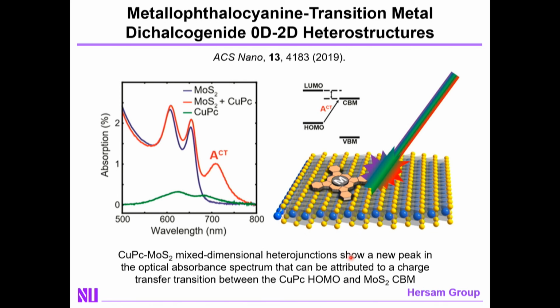This is a 0D, 2D heterostructure combining a transition metal dichalcogenide, namely molybdenum disulfide, with a metallophthalocyanine, in this case copper phthalocyanine. If we look at just the simple frontier orbitals, the HOMO-LUMO, compared to the conduction band minimum and valence band maximum of molybdenum disulfide, we see what should be a type 2 heterojunction, and as a result, you should see mutual photoluminescence quenching, which is in fact observed.